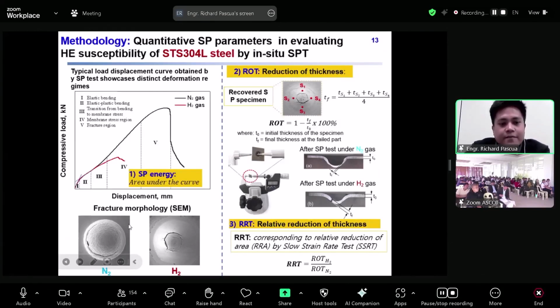As you can see, this is the typical fracture morphology analyzed by scanning electron microscope, or SEM, under nitrogen and hydrogen environments. In the nitrogen environment it showed a large circular crack with plastic deformation, while in the hydrogen environment it showed small ring-shaped cracks due to the hydrogen embrittlement effects.